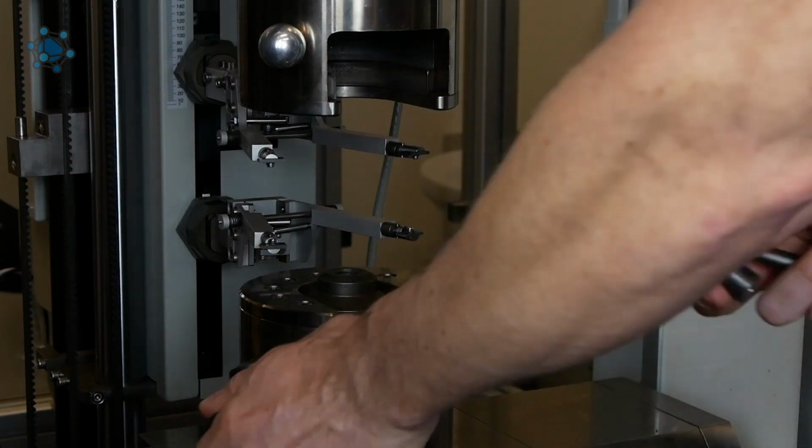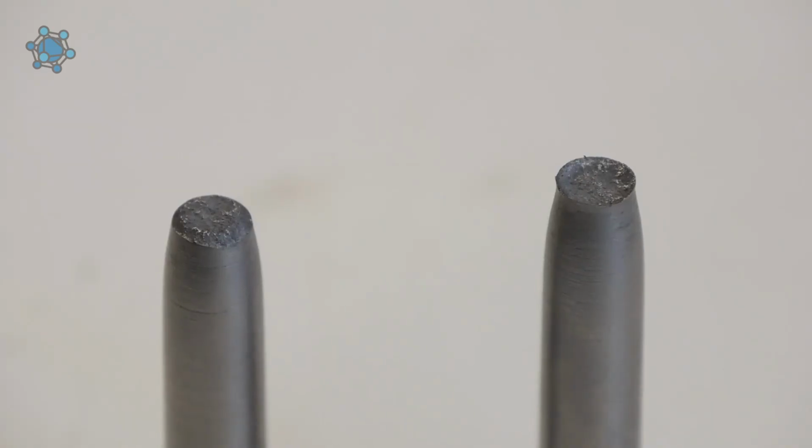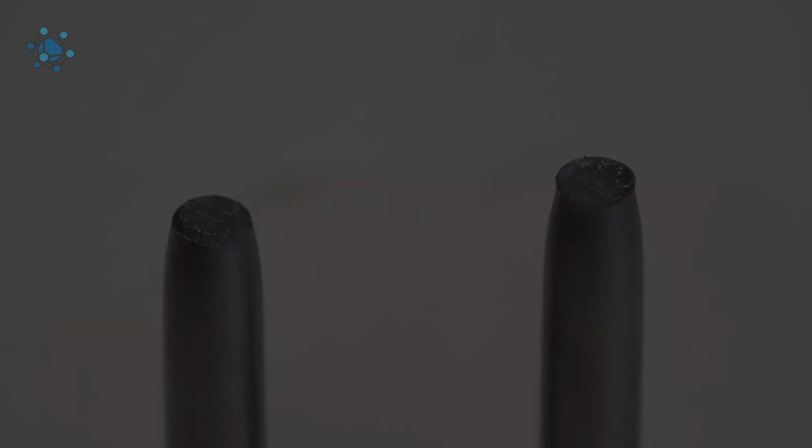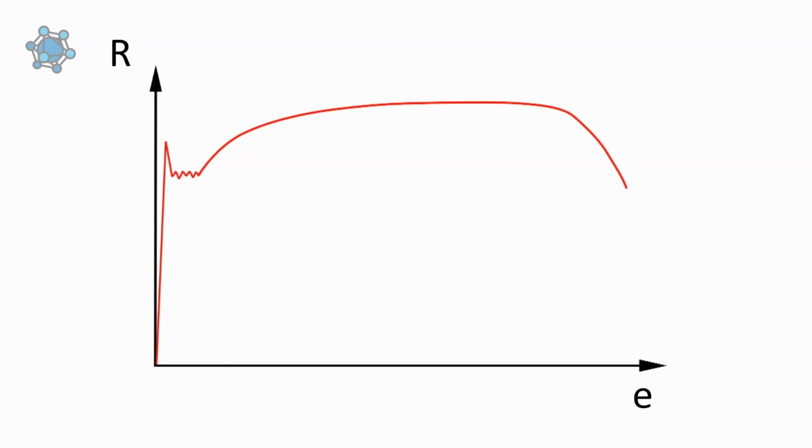We can further analyze the fracture shape where the necking occurred and recognize a cup-and-cone fracture, typically characterized by a 45-degree fracture surface at the rim and a 90-degree fracture surface at the core. Let's look at the diagram in more detail.